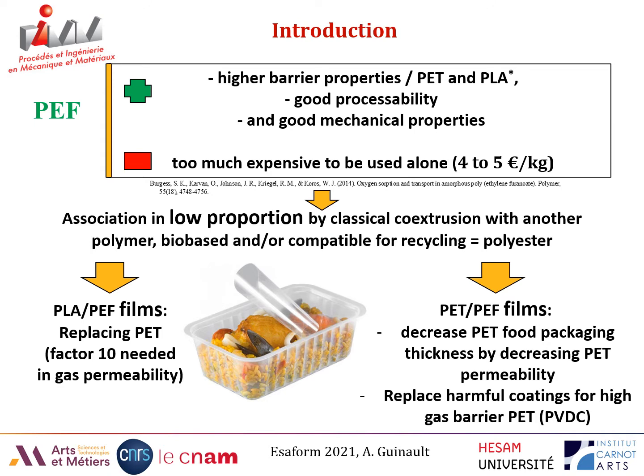PEF is interesting because it has higher barrier properties than PET and PLA, a factor 6 to 8 compared to PET and around 100 compared to PLA. It has good processability like PLA and PET, and good mechanical properties, even if it is brittle. But it has one drawback. It is too expensive to be used alone. It costs around 4 to 5 euros per kilo.